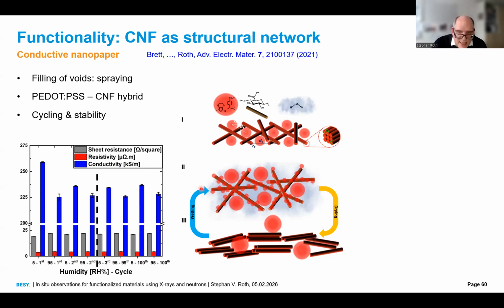And in cycles 2 and 3, we wet again, these structures become smaller, de-wetting, we dry again, we have again wetting, and structures larger. This correlates perfectly with what we see here with the cyclic humidity changes. So we can explain macroscopic phenomena, the conductivity, with nanoscale changes.